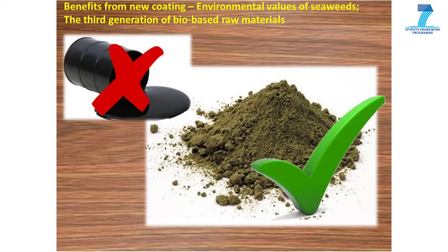The industry has met the demands of an increasingly regulatory environment by reducing VOCs in formulations. The most economical way of limiting VOC emission is using water-based coating formulations in which water replaces a substantial amount of the organic solvents traditionally used. Unfortunately, water-based formulations have deficient properties in comparison to solvent-borne ones, primarily as a consequence of using water as a solvent. Poor wood wetting, high grain raising, longer drying times, foam formation, insufficient glossy aspect, and deficient overall resistance.